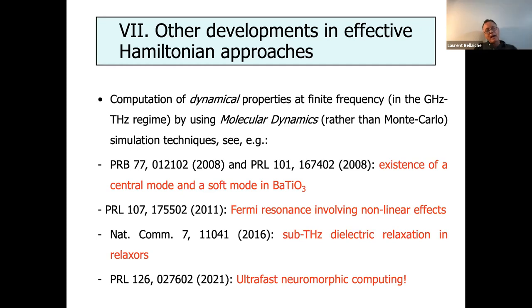A very active field that we are pursuing right now is ultra-fast neuromorphic computing. You can do that with effective Hamiltonian and molecular dynamics. In this PRL paper, for which the first author is Sergei Prosandeev, this is about PMN. What we found is that if we apply a train of electric pulses to this system, you basically mimic all the key features of neuromorphic computing, the activation, the non-volatile memory states, etc. And you do that in the terahertz regime. This means ultra-fast. So I also think that these effective Hamiltonian approaches can be very useful to provide the design of a lot of systems, including very complex ones, like for ultra-fast neuromorphic computing, which we are pursuing quite a lot.